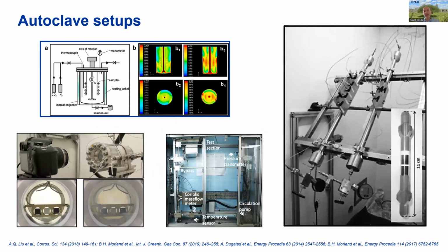So how do we test in the lab? There are several different types of autoclave setup that are used. So from simple static autoclaves where the specimens are just suspended in the autoclave, the fluid isn't moving other than being stirred to ensure that the environment around the specimens is constant. Then I note that Monica's already showed this nice setup from IFE where they have a camera with a transparent window in the autoclave. And this has been really useful for studying the phase behavior of the water, what you can see using the camera and the transparent window, where we get condensation of the water and when, as a function of the conditions in the autoclave.